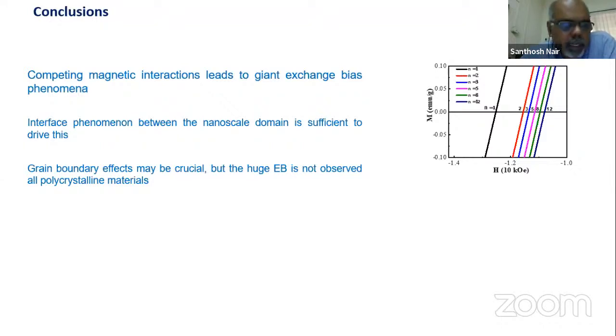What we find is that in a double perovskite, maybe iron and cobalt order at least partially, but in our diffraction studies, both our first system and this system are randomly ordered. So I don't know whether I can call it two different sublattices. Probably you can. It's a severely disordered system, so you would expect a competing magnetic interaction. But then you do not see exchange bias, right? That is very interesting. We don't see an exchange bias.